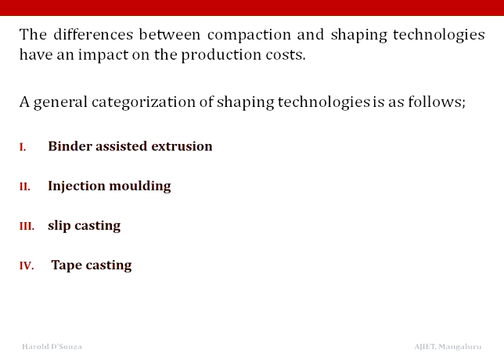The differences between the compaction and the shaping technologies have an impact on the production costs. Important considerations are the component size, the desired final density, and shape complexity. A general categorization of shaping technologies is as follows. Binder assisted extrusion: elongated parts, fine powders, constant cross section, and relatively simple shapes. Second one, injection molding: it's for complex or small components or high performance materials. Slip casting: it's for very large structures, constant wall thickness, and low precision. And tape casting: used for flat sheets, very simple shapes, and fine powders.